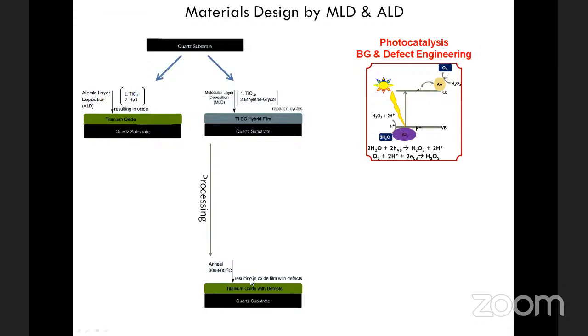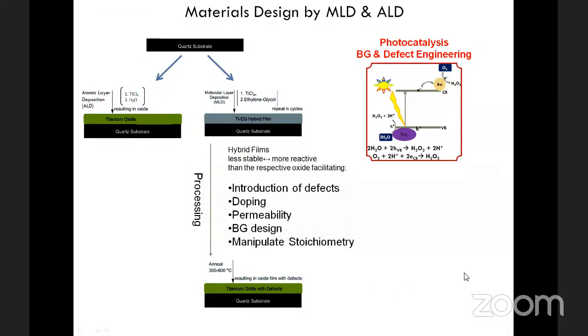So for some reason, we chose to take the long way of attaining the oxide by making an intermediate organic inorganic hybrid film. The idea behind this was that having this hybrid film, which has the organic functionalities, would have metastable or less stable properties compared to the pure oxide, which is a very stable material. And this will allow us to do all kinds of manipulations, as you can see here.